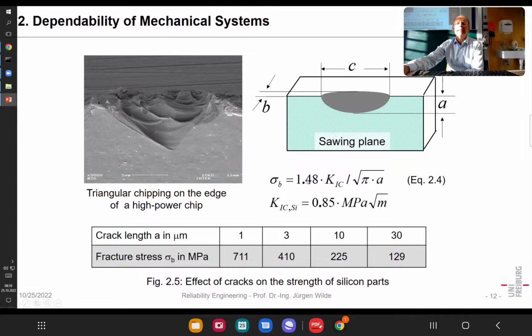Also, window glass has a similar fracture toughness like silicon, for instance. Many say the most important part for silicon is that it is separated at crystal planes. That is partly correct, but the most important part is that low fracture toughness. On the other hand, a quite tough steel can have a fracture toughness of 200 megapascal square meter. So, okay, a crack is something dangerous.